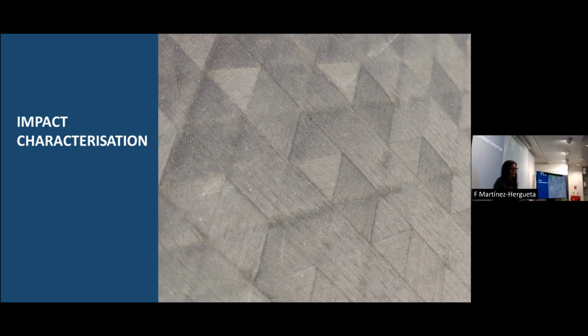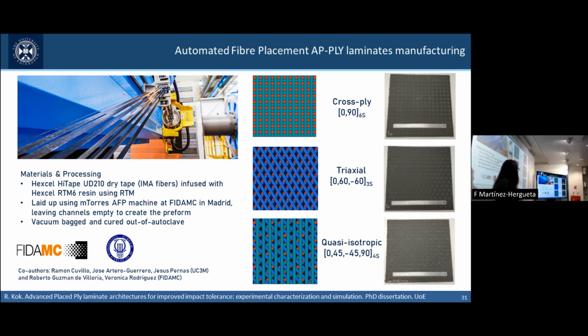And finally, this is what I initially came to share, which was the impact characterization. This was finally manufactured on a real AFP machine in Madrid. So there is a foundation for composite materials there. It's mainly sponsored by Airbus, where they've got an MTorres equipment that we use to manufacture these composites. This machine has 8 channels for tows. The approach we used to manufacture the AP-PLY laminates was to empty half of these channels in order to create the gap. So the gap that we are using here is not 3 tows. We are just leaving one single gap. That means that if our machine had 8 channels, we were just using 4 of them.